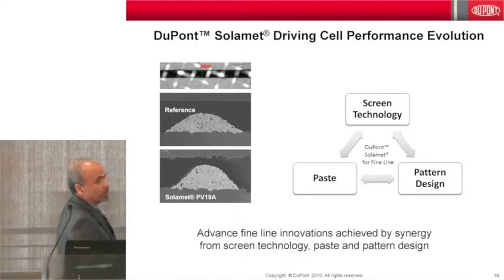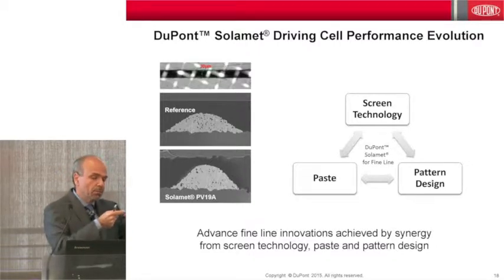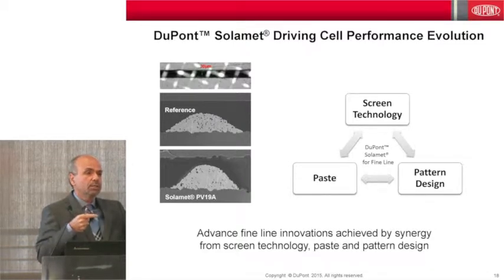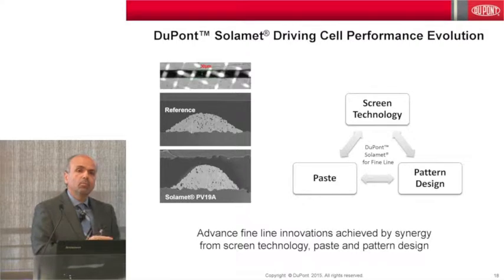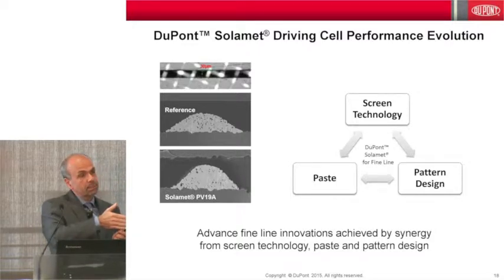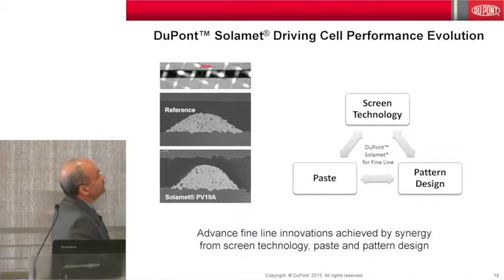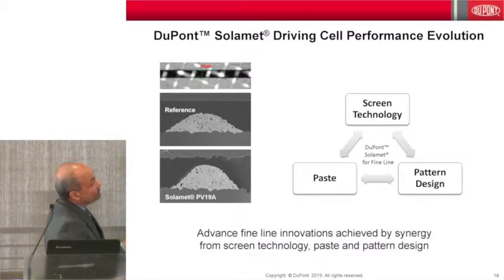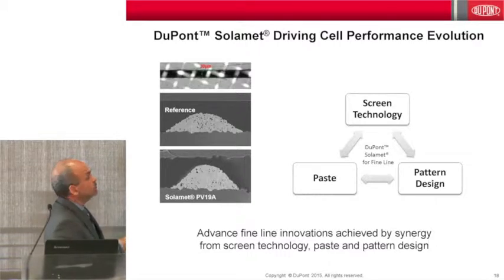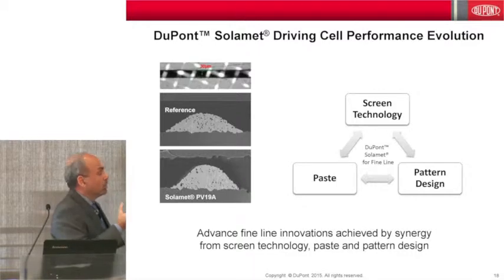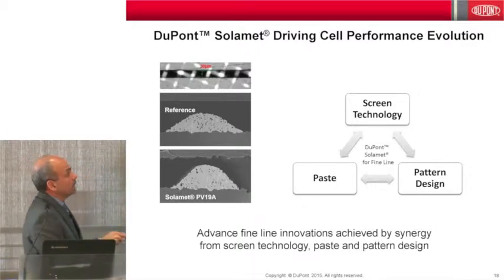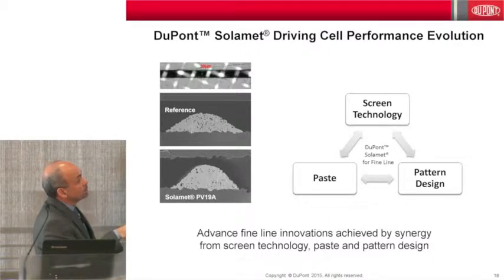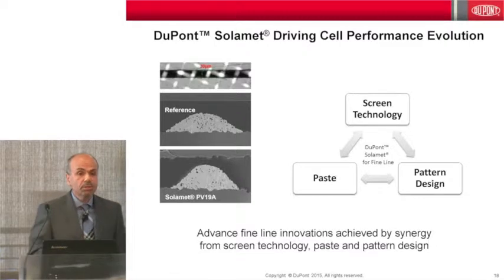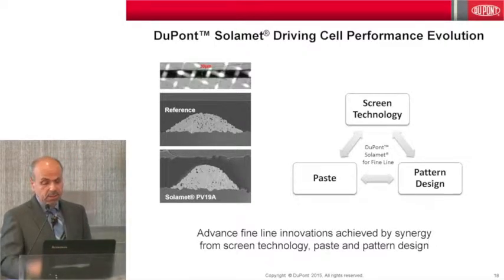Some of the hard problems that we're trying to solve: what you can see there is the cross-section of the silver. Imagine that you have these finger silver lines on the crystalline silicon, and the silver tends to spread, and the more it spreads, the more it will shade the light. So what you want is very tall silver lines and very narrow lines, and many of them. Although it sounds trivial, it's a very hard problem. In the past year or two, we have been able to narrow the width of the silver by 10 or so microns. We have done this by working closely between the screen technology, the paste formulation, and of course, different pattern designs of the cell.